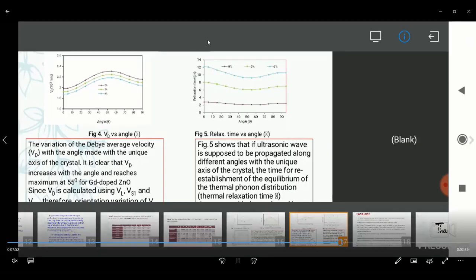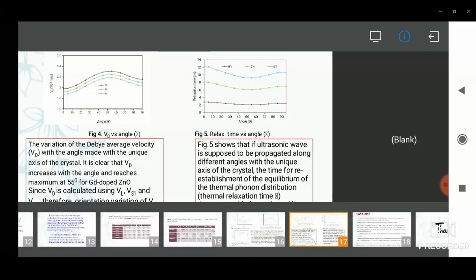Figure 5, relaxation time versus angle. In Figure 5, the ultrasonic wave is propagated along different angles with the unique axis of the crystal. The relaxation time is the time taken to re-establish the equilibrium of the thermal phonon distribution.